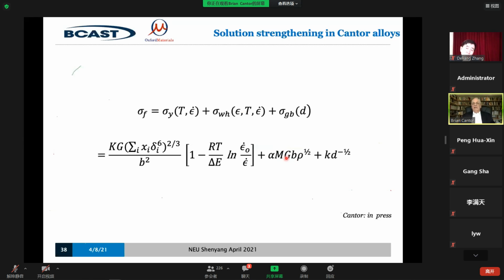Work hardening is proportional to the square root of dislocation density. This is grain boundary hardening, which is proportional to 1 over the square root of grain size. So we know about these. These are absolutely standard. The special feature is this one. This is the one that's much higher, the basic yield strength.